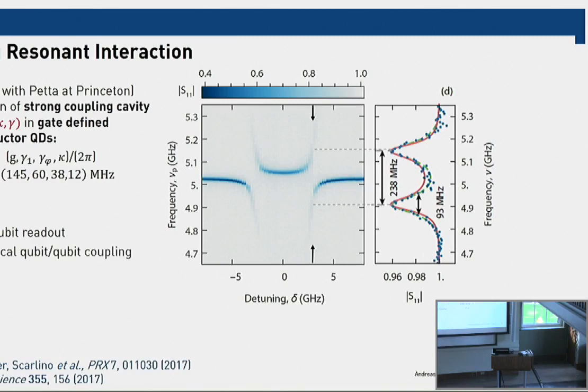Operationally, how do you figure out delta? You're tuning some voltages and then... You look at honeycomb diagrams, and you can calibrate how the levels move around with respect to the voltages, and there's cross couplings between all the elements. And so that takes a little bit of experience to do it, but in the end you can calibrate delta. And what is also nice is that the resonator itself introduces a fixed energy scale, which you know, and then you can refer everything to this fixed energy scale, and look at what voltages different states come into resonance with this resonator. I could show you some pictures.